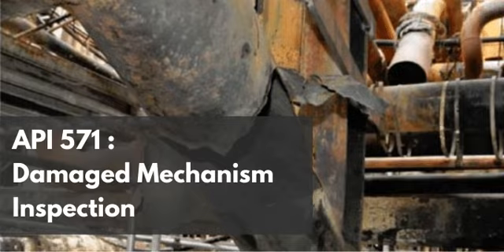General corrosion is a predictable adversary, right? Yeah. It consumes metal uniformly. You can just track it with standard ultrasonic thickness readings. Exactly. You plot a corrosion rate, calculate a retirement date with a reasonable degree of engineering certainty. But Amine SCC operates on an entirely different metallurgical plane. Because it leaves the bulk thickness totally untouched, doesn't it? It does. You could have a section of carbon steel pipe that mics out perfectly to its nominal wall thickness. It looks immaculate from a macro perspective.